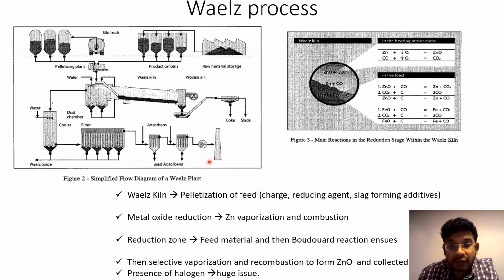So the selective vaporization, the first step being the reduction, the following step is the selective vaporization here, okay? The key problem here is that it's a very simple and effective process, except that it's a bit energy consuming. And of course, in reality, a lot of it is fueled by coal. But barring that, it's a very effective and efficient process, and it's quite selective as well, because you essentially vaporize and then collect it in the oxidation zone, right?